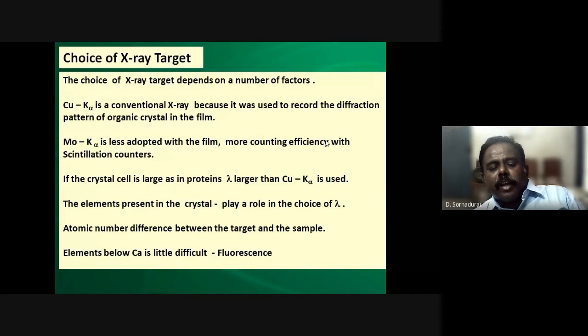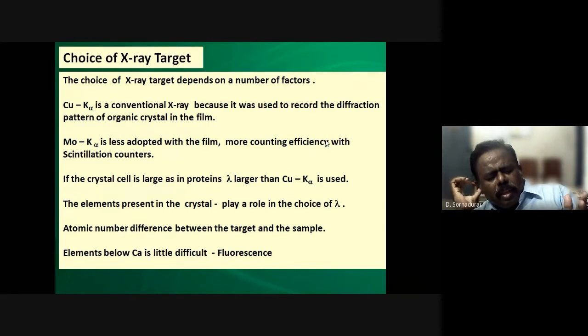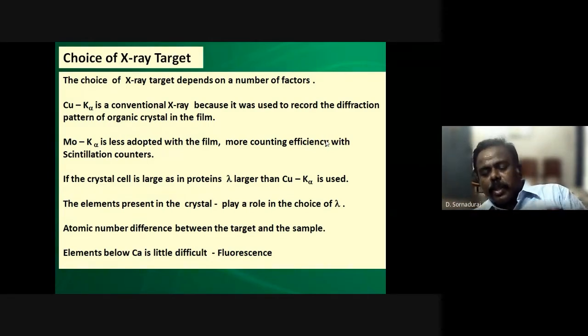Finally, the atomic number difference between the target and the sample. If you use a sample very close to copper, like iron, iron will give a lot of fluorescence, so it will not give any proper diffraction. Similarly, elements below calcium are a little bit difficult because of the fluorescence.